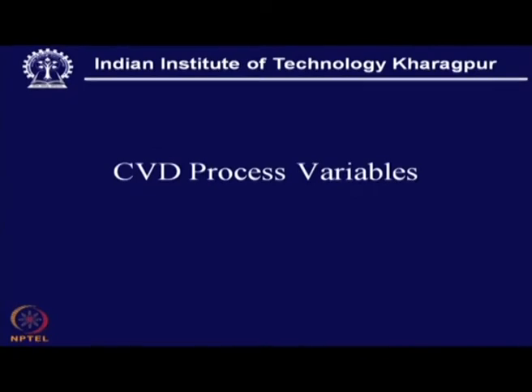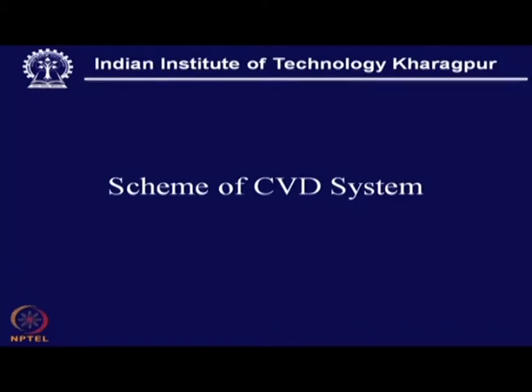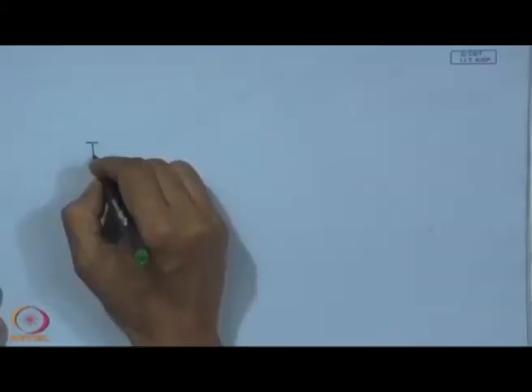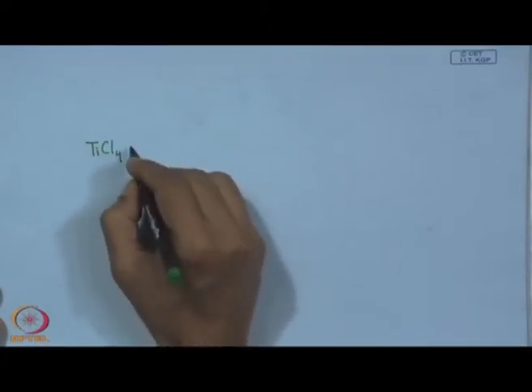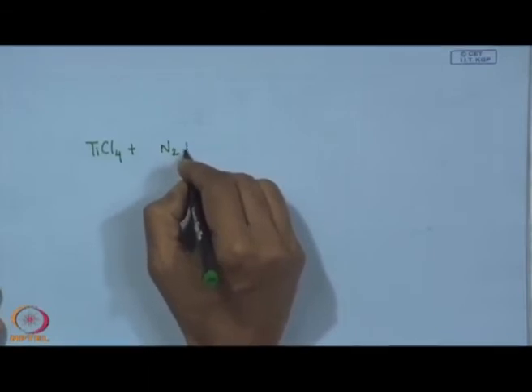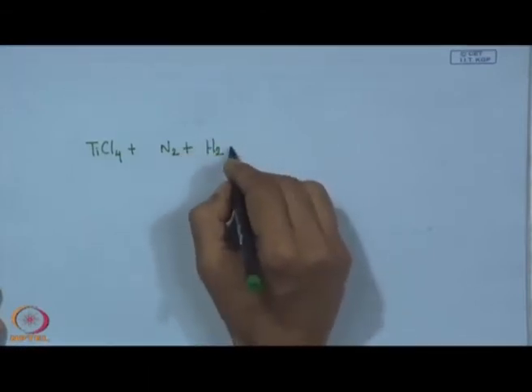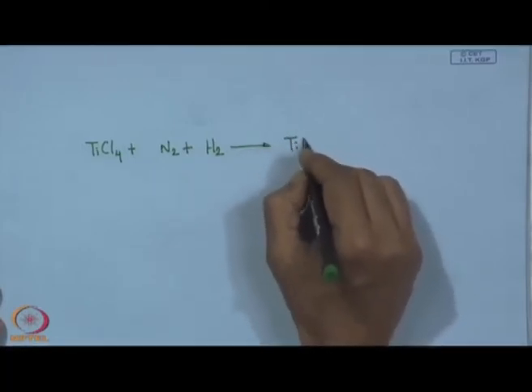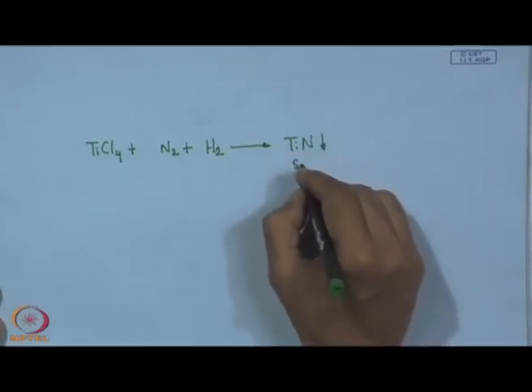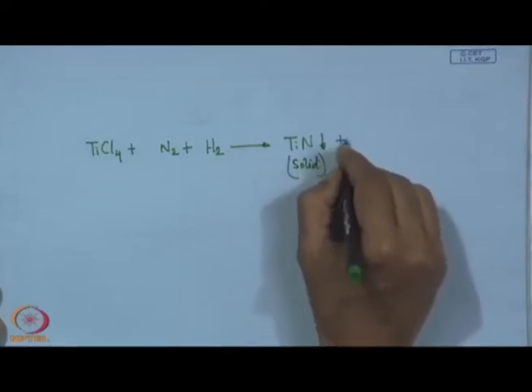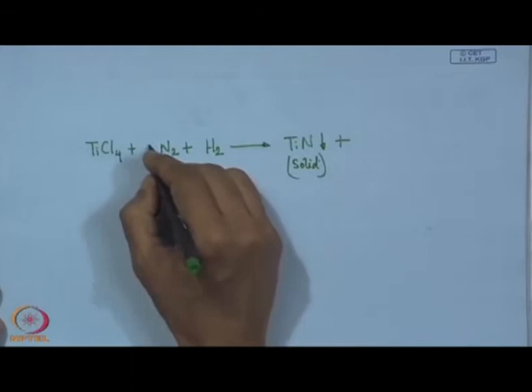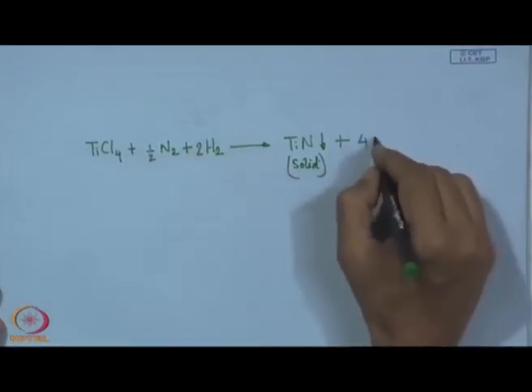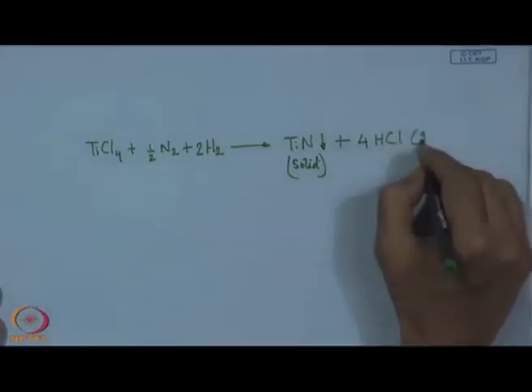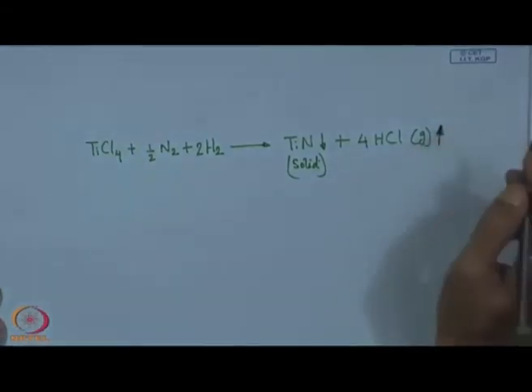Now, this TiN coating can be carried out by following a CVD reaction scheme. Here we have titanium tetrachloride plus nitrogen plus hydrogen, which will give TiN, which comes as the coating, that means it is solid, plus 4 HCl, which is a gas that should escape this CVD reactor or CVD system.